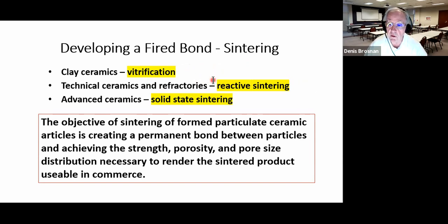In technical ceramics and refractory, the chemistry may be much more pure. I know there are clay refractories, but in the general case, there are much purer ceramics. We've controlled the purity and manufacturing. And so typically we'll use higher temperatures in producing these types of ceramics, above red heat. And in advanced ceramics, we can really achieve sintering maybe as hot as white heat in a kiln, when the visible emission from inside the kiln lining is white in color. You know that you're very close to 1700 degrees Celsius, maybe 3200 degrees Fahrenheit. Whereas remember, red heat was down here close to 1000 degrees Celsius when you can see it.